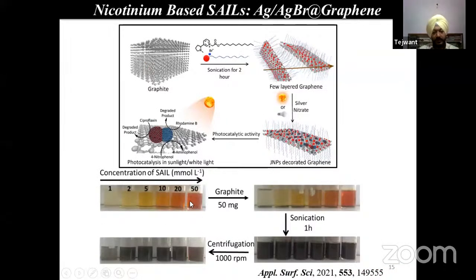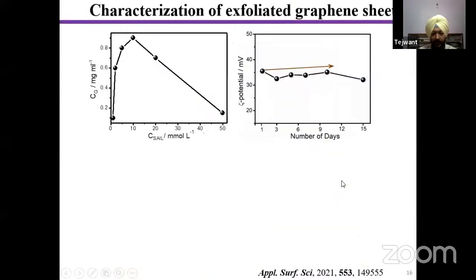So this is the figure showing the exfoliation of graphene. Okay, I'll skip this. Then we have found that we have to establish the exact concentration of surfactant which we need for the maximum exfoliation of graphene. It was found that when the concentration was very close to 10 millimolar, the maximum amount of graphene can be exfoliated, and the exfoliated graphene has been found to be very stable in aqueous medium as a function of days.